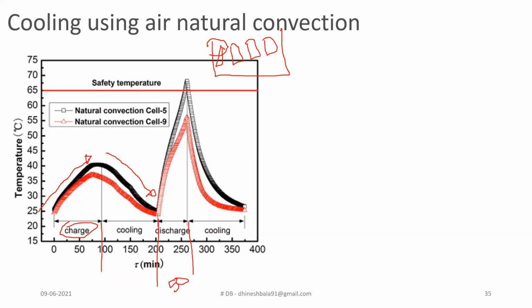That is, from 100% state of charge down to 20% or 10%. So what they are trying to do is completely drain your battery percentage from 100 to 20% in the next 5 minutes. If you discharge the battery at a very fast rate, what actually happens is there is a huge temperature range.